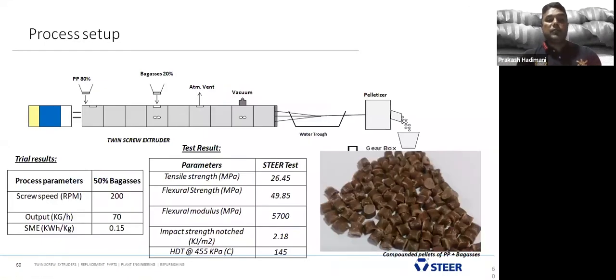With the similar 50% of bagasse, we fed polymer from the intake and melted it, and fed bagasse from the side feeder. And tensile strength, if you compare to jute and others, bagasse had a little bit lower tensile strength compared to jute. Jute is giving almost 55 MPa, but we are getting lower. But flexural strength was good in terms of bagasse, and flexural modulus also almost near to the jute, and impact strength is the same. One interesting thing we observed was the HDT. It was a good one, 145°C. And we didn't find any issue in the process, and we get good pellets from the bagasse.